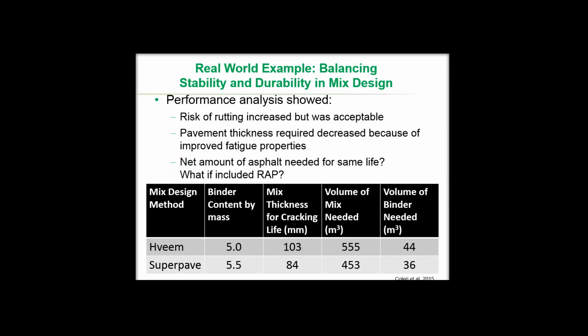However, by increasing the fatigue resistance of the material, we could reduce the thickness and still get the same cracking life. So then the question was, what's the net impact of increasing the binder content but being able to design a somewhat thinner pavement? So, apologize for the metrics here, but by increasing the binder content from 5 to 5.5%, the mechanistic design indicated that we could reduce the thickness.